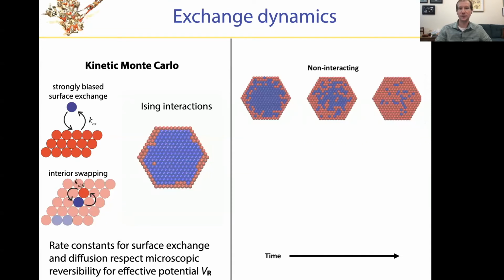Let's next move to the model that I said was equivalent to a liquid boiling, a conventional phase transition, the so-called Ising model. This is just describing the local chemical preferences of each of these materials to be next to itself or to be next to the other material. And now we see a very different character of exchange. We see that exchange proceeds fairly rapidly over the first few layers and then halts.